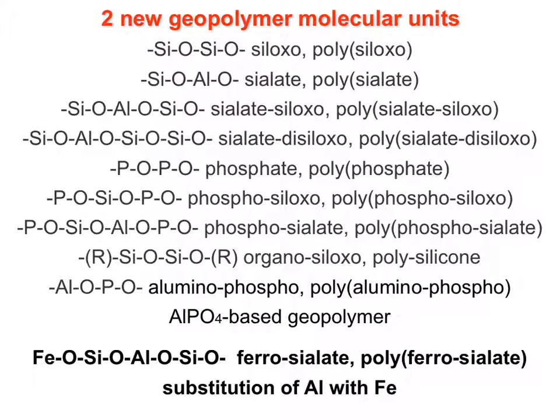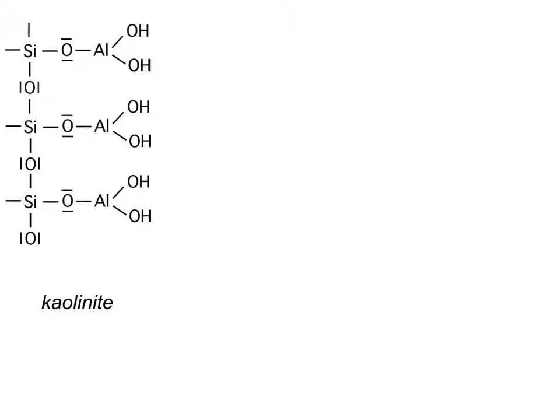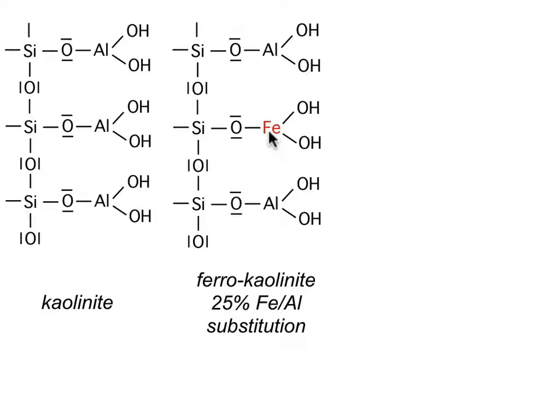The second unit is what I call the ferro-sialate, FeOSiOAl, polyferro-sialate, and is a substitution of the aluminum atom with iron atom. This is a chemical structure of kaolinite. We have the polysiloxo chain and branched aluminum hydroxyl groups. And the ferro-kaolinite has, instead of aluminum, 1 atom of iron. The substitution of aluminum may happen at most up to 25% of the entire structure.